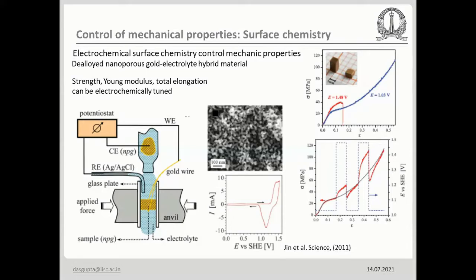The blue curve here is when it is pure gold sponge. The moment we have a little surface oxide electrochemically, then it is brittle. So you can go between these two phases at will, just by applying an electrochemical potential. I put one potential, there is a surface oxidation. I put another potential, the surface oxide is gone, and in one case it's ductile, and it can sustain a lot of strain. In the other case, it's hard and brittle. So even that mechanical property, people have now shown, can be reversed by an external stimulus very nicely back and forth.